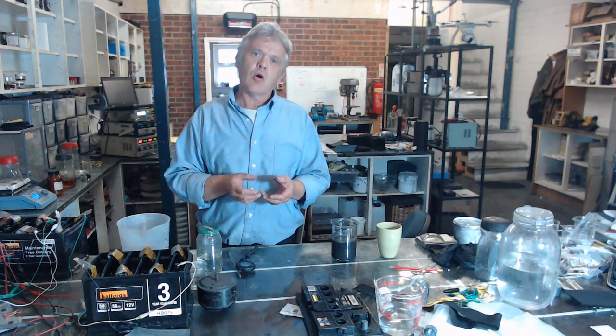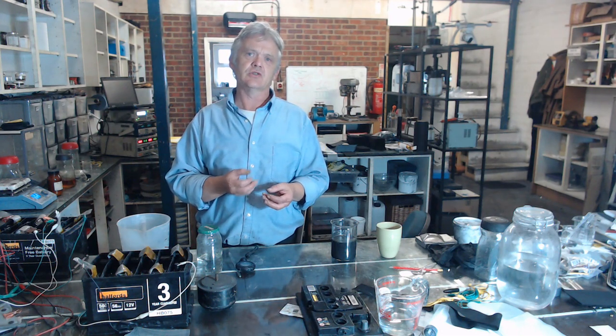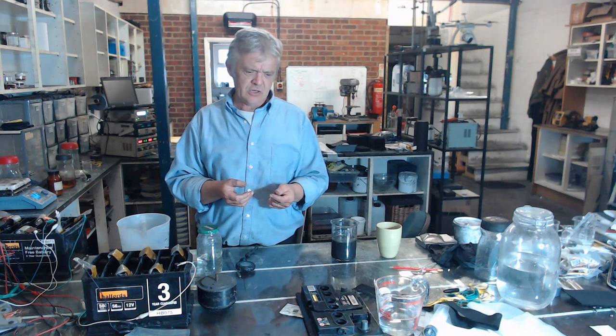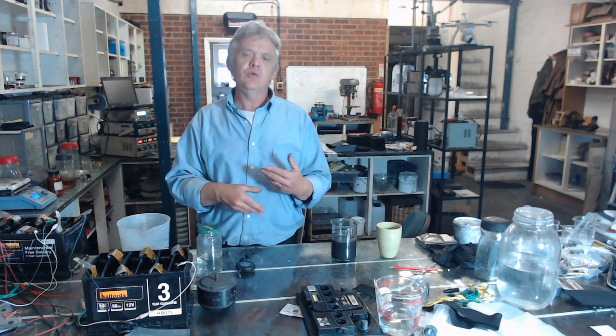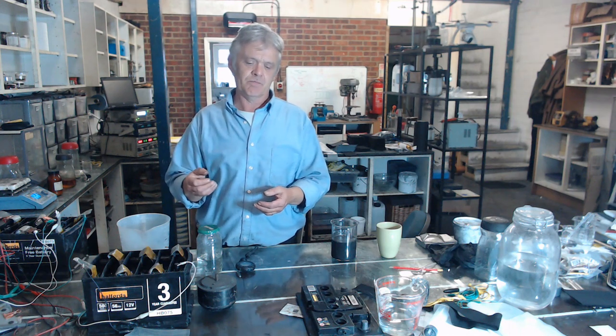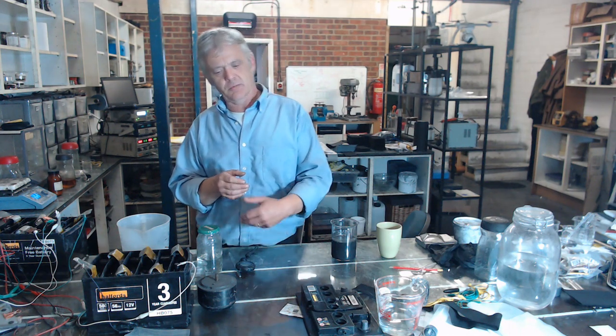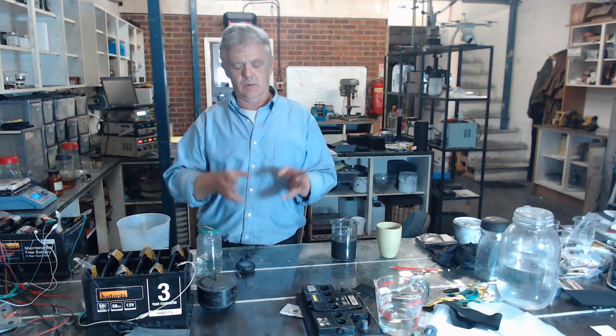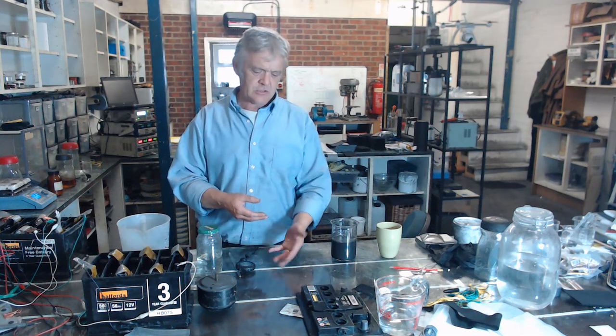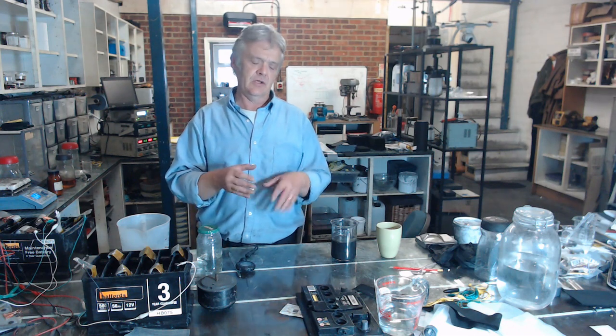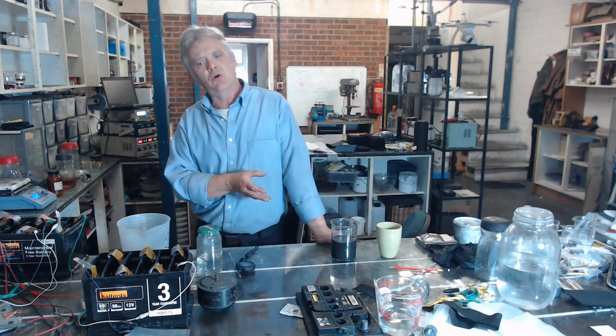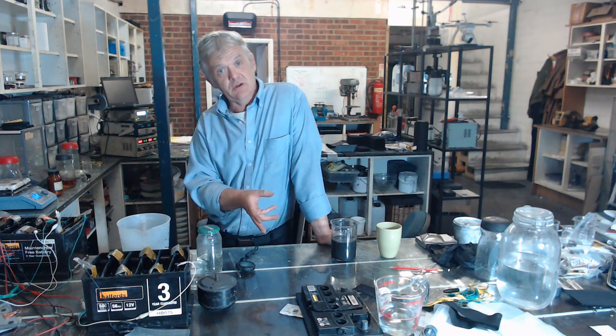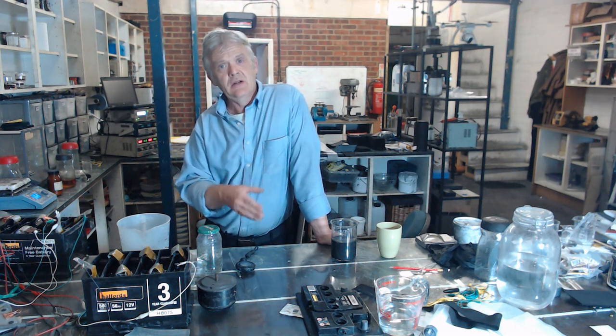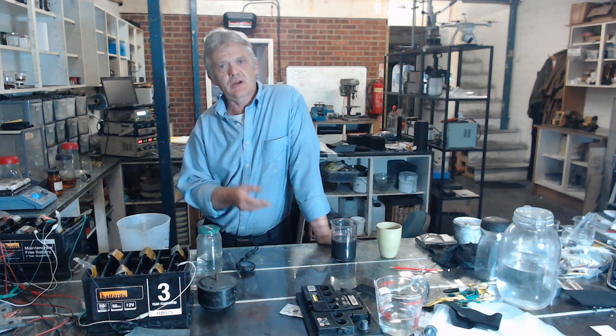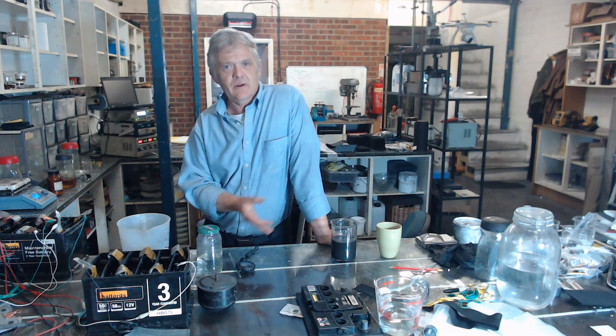Now, there will be rock bound in with some of those graphite flakes, because you can't crush it all down to the right size. So very often they do that, and then do it again. So there are two wash processes. The first wash process, everything that drops to the bottom is scraped off, and those are your tailings, and they just get chopped away. On the second, the stuff that's at the bottom is called the middlings, and they can have a value, and the final stuff can be as high as 94% concentrated graphite, and that's called graphite concentrate, and that's the stuff that tends to be characterized for later sale. So dig out of the ground, basically crush it, float it, clean it, and that's what you get.